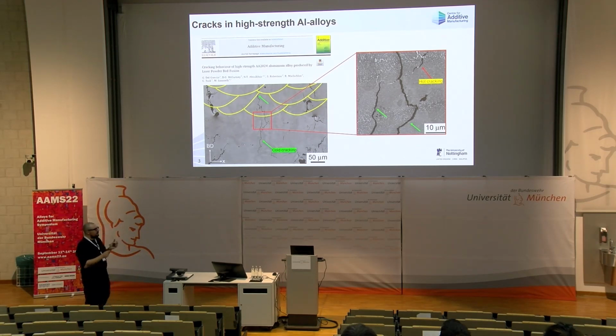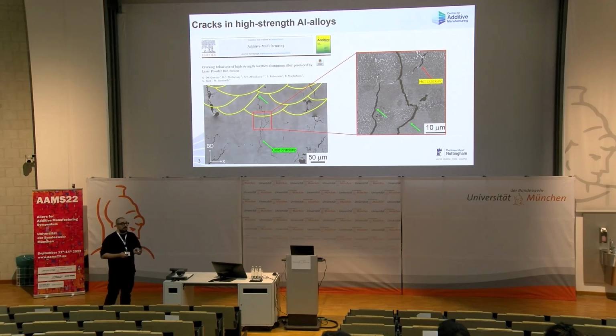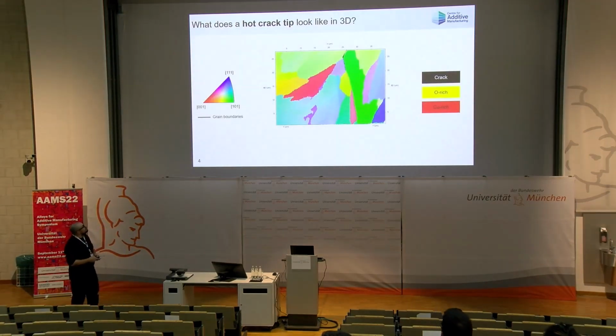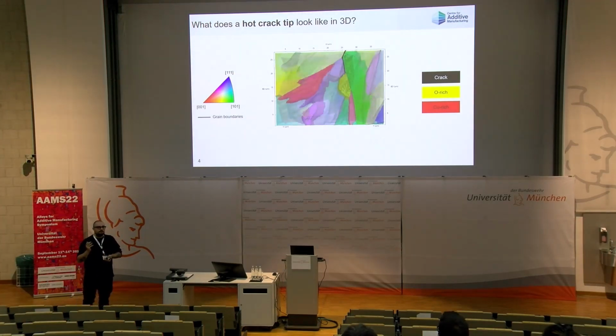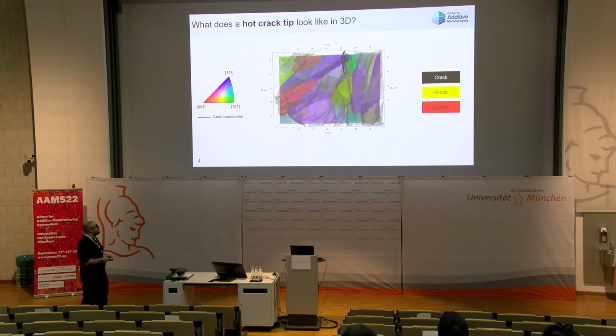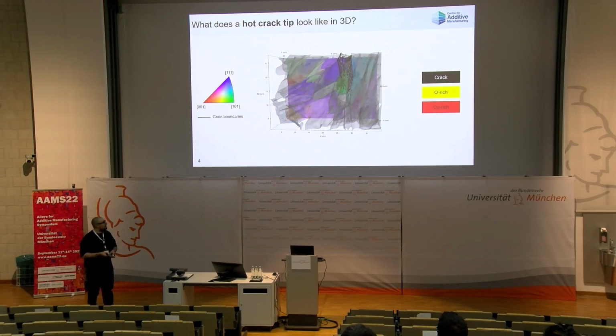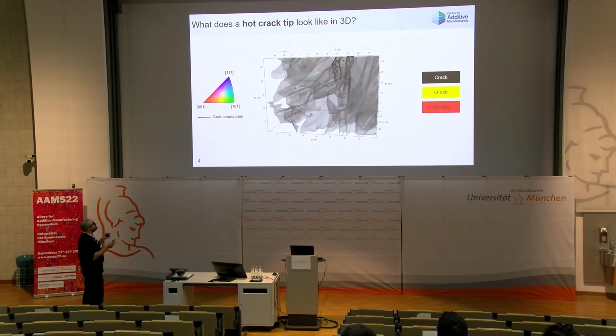So it was crucial at the beginning of my research to isolate these features and to understand what are the microstructural and chemical features that are affecting this nucleation. So what we did is a 3D reconstruction of a hot crack tip with the specific aim of understanding what is the grain orientation to the left and to the right of the cracks, but also what are the chemical profiles found at the cracked surfaces.